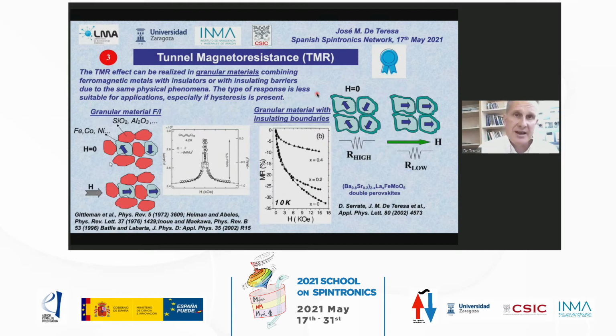Similarly to the case of giant magnetoresistance, the same tunneling magnetoresistance effect can occur in granular materials. So some groups prepared granular films with ferromagnetic materials such as iron, cobalt, or nickel, and then insulating grains such as silicon oxide, alumina, and then in zero magnetic field, the magnetization is randomly distributed, and under application of magnetic field it is parallel. So one finds a change in resistance between zero field and a magnetic saturation field of this granular material.